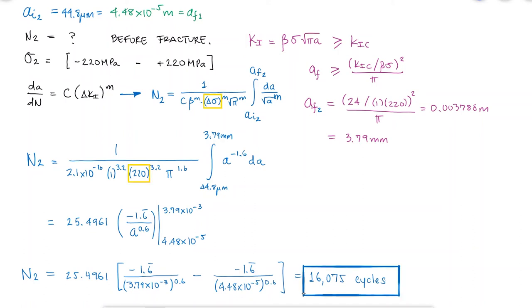Notice that the stress range that I used for the alternating tensile and compressive stresses is only 220 MPa. Using 220 MPa instead of 440 MPa is a reasonable assumption since the compressive stresses will have little to no effect on the actual growth of the crack.